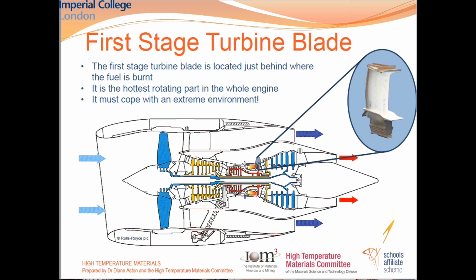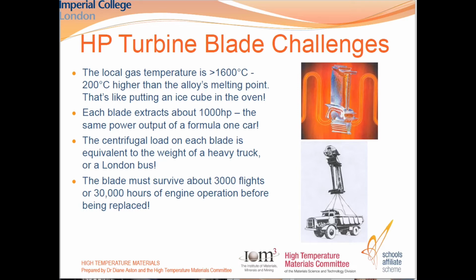Now, the first stage of the turbine, the one that I talked about, the one that has to withstand the hottest, harshest environment within the entire engine, is located right behind where the fuel is burned, and it's the hottest rotating part in the engine. It must cope with the most extreme environment. So here we will have some considerations of what to make them out of and why. Now, the high pressure turbine blades need to operate at about 1,600 degrees C, which is quite interesting because it's 200 degrees above the alloy's own melting point. So if you've ever been on a plane and you can see the engine outside, each line of these blades inside the engine needs to be above its own melting point and still be strong and last. This is like putting an ice cube in the oven and expecting it to stay solid. It's a very difficult engineering challenge.